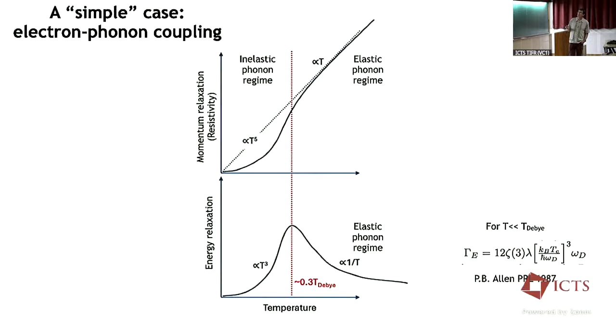So let's take a simple case of electrons coupling to phonons. We can compare the momentum relaxation rate and the energy relaxation rate. The momentum relaxation rate, at least in the textbooks, for electrons scattering off of phonons goes like T to the 5th at low temperature. And then at some temperature, which is of order some fraction of the Debye temperature, it goes linear in temperature with a coefficient very close to 1. And that's important for some of our discussion, which will come in a bit.